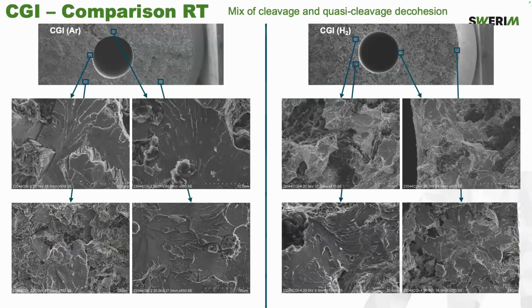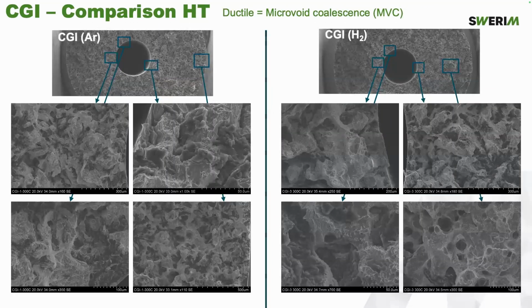Some snapshots from the fractography comparison between temperature, argon and hydrogen. On the left you have argon and on the right hydrogen. What can be seen is typically very similar behavior regardless of the type of gas. We have a mix of cleavage and quasi-cleavage decohesion. For high temperature CGI, namely a ductile type of behavior, we have definitely a microvoid coalescence mechanism of fracture. And this is actually a first indication that supports the SSRT result.